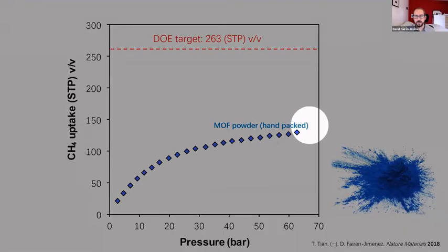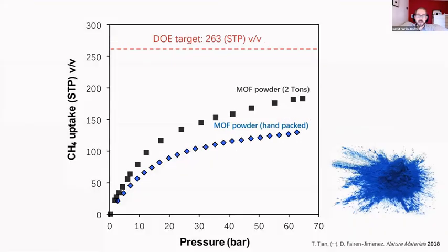They basically took this powder that you can see here on the right and tried to compact it by hand, with the pressure you can apply with your hands, and that was the absorption isotherm, okay? Up to 65 bar. This is very far away from the Department of Energy target, but it's a very, very high absorption capacity. This is taking the same powder and compacting it up to 2 tons of pressure. They are able to densify the material, and therefore the volumetric capacity increases because the density of the material is increasing as well. Okay, 2 tons is still not very high.